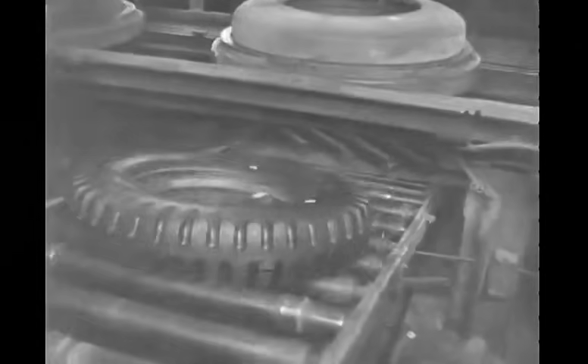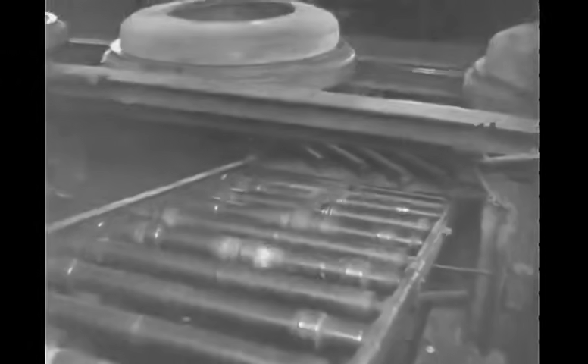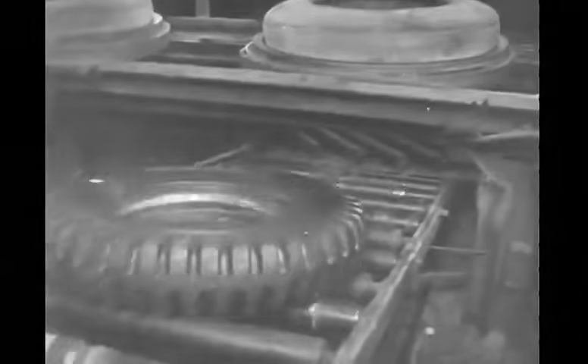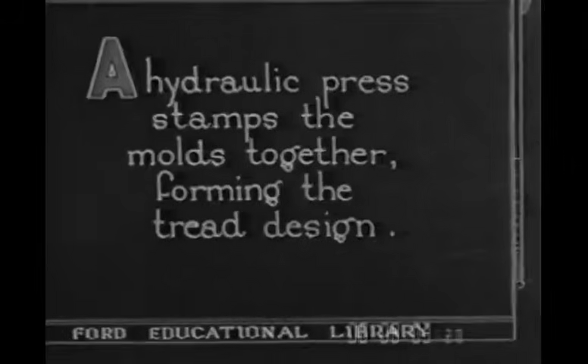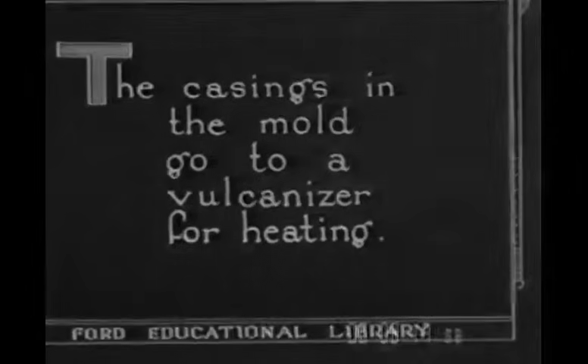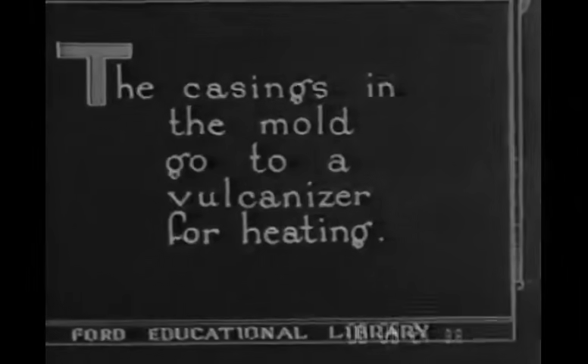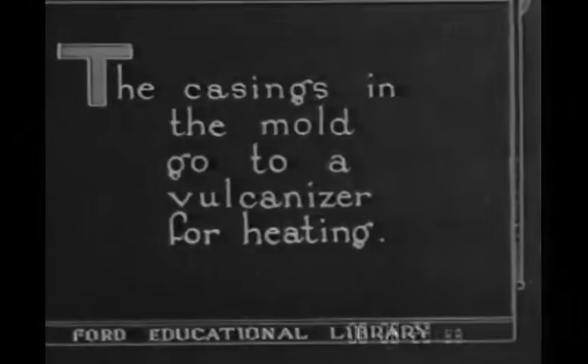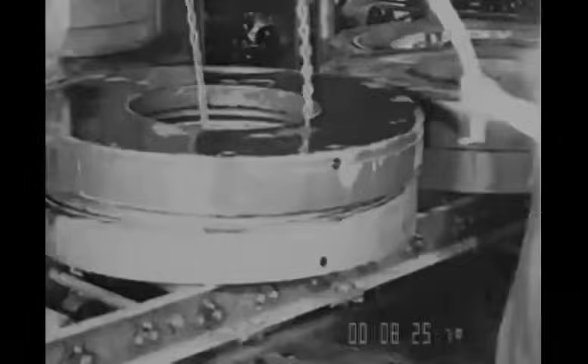Yet, even when the bales accumulated, the real test had not begun. The nation did not need warehouse rubber. It needed tires that would not fail. GRS resisted abrasion well, which made it promising for tread. But compared with natural rubber, the early material was less tacky in its uncured state. Tire construction depended on layers sticking together before vulcanization. If the components shifted during building, the tire could contain hidden weaknesses.